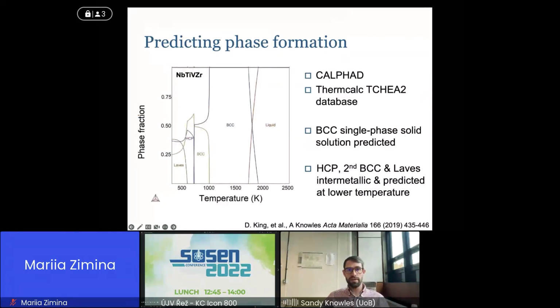So having defined these compositions in this system, we then applied CALPHAD to try to see how well it does the prediction. It predicted that there does exist a single phase. As we go down in temperature, first you're liquid, then you form solid BCC. There's a large temperature range in which BCC is stable, or at least the predictions say. Then at low temperatures, we might get some mixture of phases between Laves, 2nd BCC, and HCP.